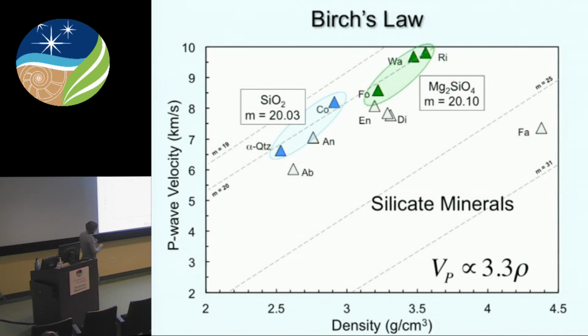And so what you can see here, this is the silica polymorphs, quartz and coesite, and up here we have our friends forsterite, wadsleyite, and ringwoodite. And you can see, to a first order, they lie along these lines of constant mean atomic weight, whereas you increase density, whether it's through composition or through structural changes, you have this very predictable collinearity. And this is what's seen and predicted in equations of state like the Birch-Murnaghan or the Vinet.